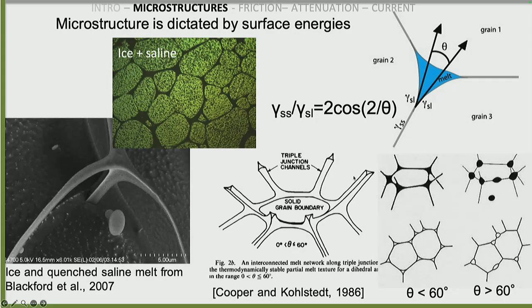And if you don't believe the little cartoon here of what this three-dimensional network might be like, hope you believe this image taken by Jane Blackford, where she took ice plus saline, which is very similar to what we've made, and put it in the SEM, quenched it. So liquid nitrogen quenched the saline. And then in the SEM, the ice, which is this gray mottled stuff, sublimated faster than the quenched melt. And so you could see that really crazy looking network there.